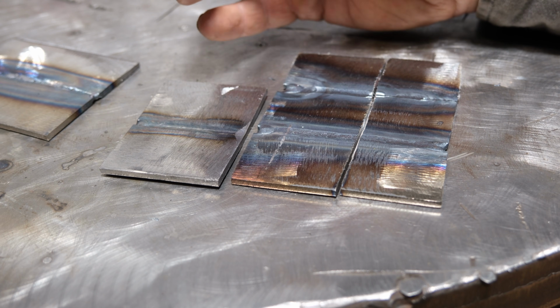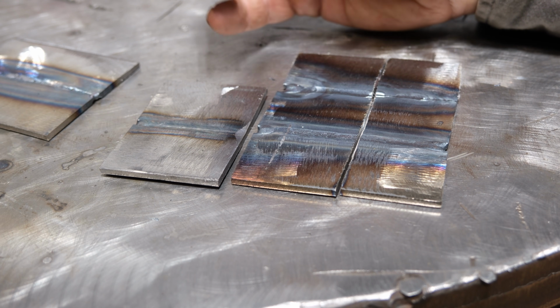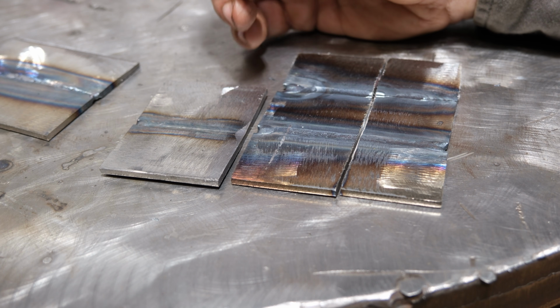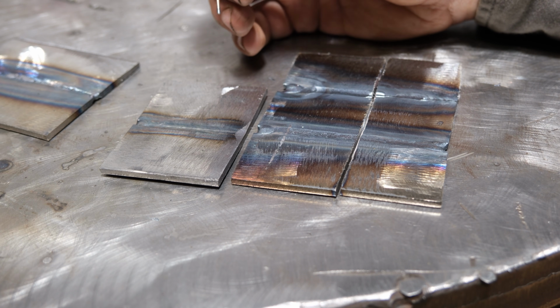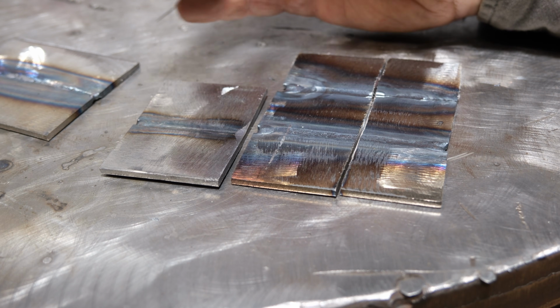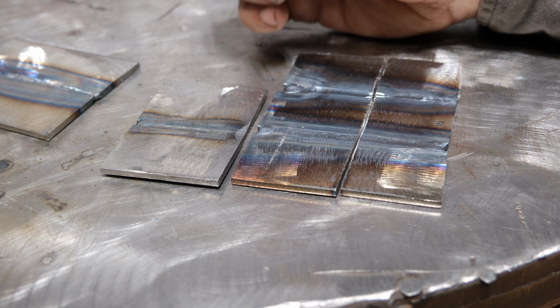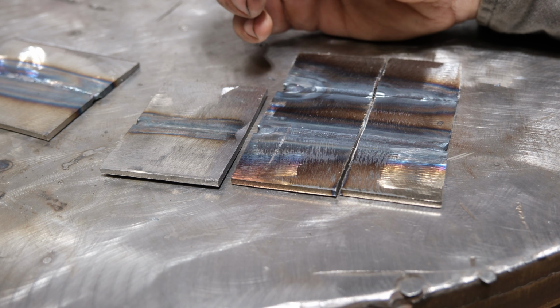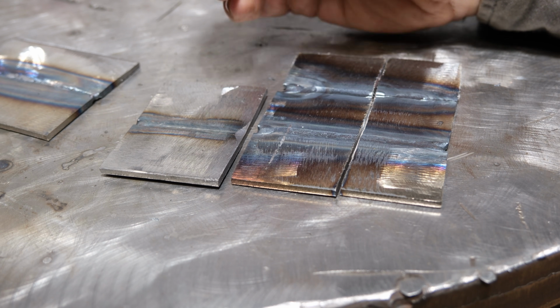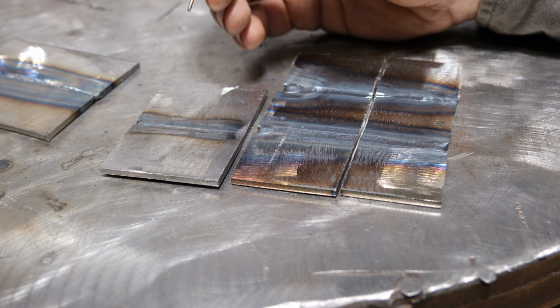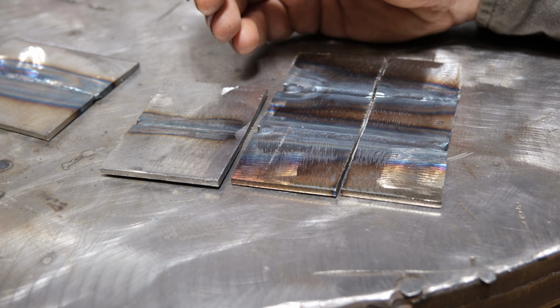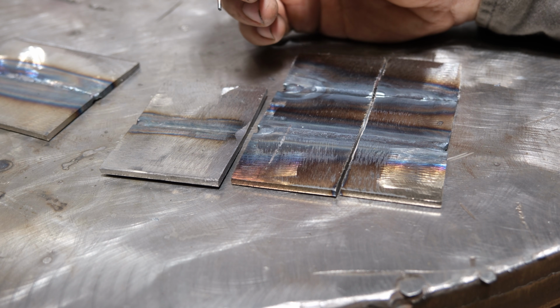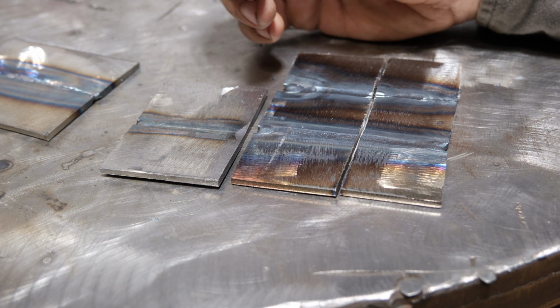Now, going back to the whole fusion versus filler weld argument, I personally do not make a habit out of doing fusion welds on anything except for very thin material, typically on outside corner joints, because it works well in that case. When you don't add filler, the risk is, well, for one, you might move too fast and lose penetration. That's not good. Two, arguably, the alloy of the filler rod being added would likely make the weld stronger than the base material, and that can be a good thing in a lot of cases.